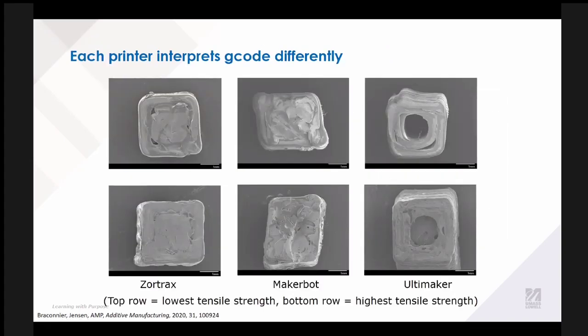We think that what has happened is related to how each printer interprets G code. Even though we tried to make everything as consistent as possible, when you tell 3 different printers to make a dog bone, they're going to interpret that information differently. Here you can see some fracture surfaces of the dog bones, and again we'll get into this issue of toolpaths. In the Zortrax, there would be a single road wall that was created, and then there would be extrusion in the middle, and it would always start and stop from the same location.